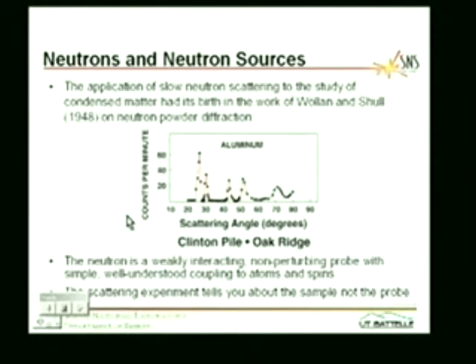Using neutrons to study condensed matter in the sense that we now do it really had its birth in the work of Wollan and Shull on neutron powder diffraction. This was carried out in Oak Ridge using the graphite reactor, or the Clinton pile as it was called. And this figure shows some data taken from their 1948 paper in Physical Review on neutron powder diffraction, where they've plotted the intensity in counts per minute of a monochromatic beam of neutrons scattered off a sample of polycrystalline aluminum, plotted as a function of scattering angle.